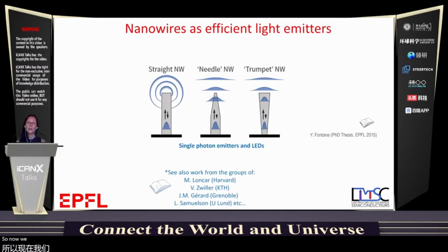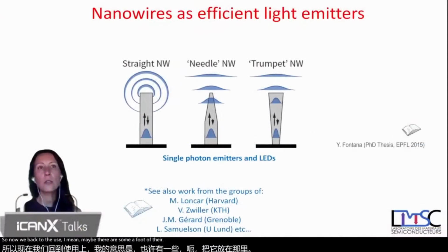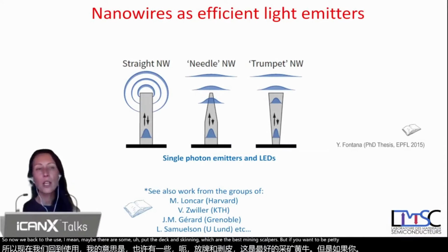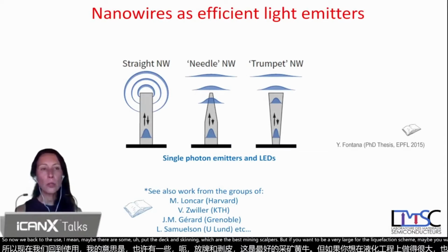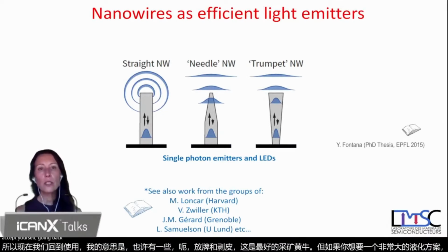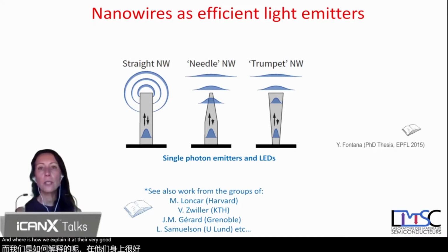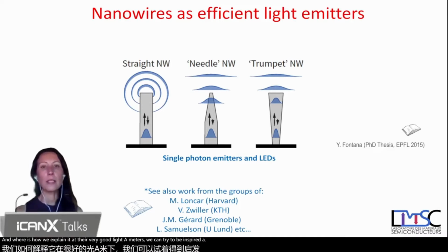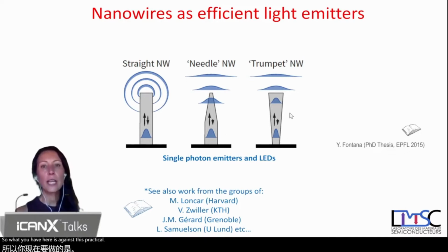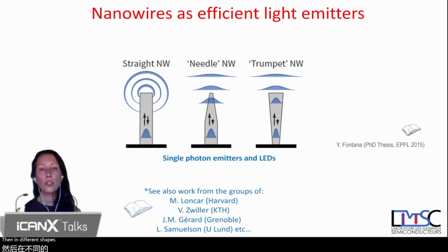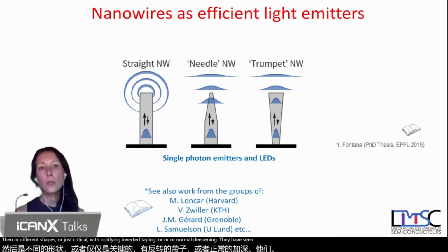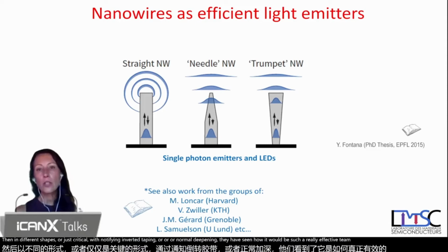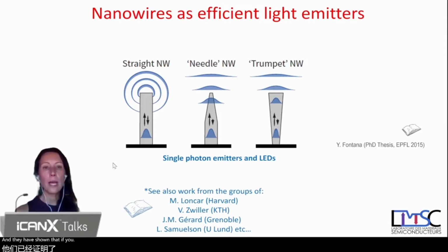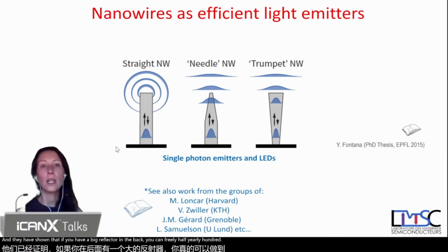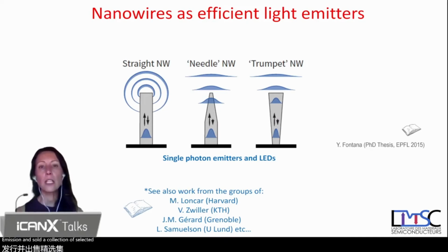So now going back to this, maybe there are some photodetecting schemes in which the plasmonics help us. But if you want to have a very large photodetection scheme, maybe you want to have something that doesn't require this plasmonic structure. So going back to these nanowires, how I explained to you that they're very good light emitters, we can try to be inspired by this. So what you have here is, again, these vertical nanowires, and people have studied them in different shapes: just vertical with no tapering, inverted tapering, or normal tapering. And they have seen how these structures really affect the direction in which the photons are emitted. And they have shown that if you have a back reflector in the back, you can have nearly 100% emission, so collection of the light that is emitted by photons inside the nanowire.